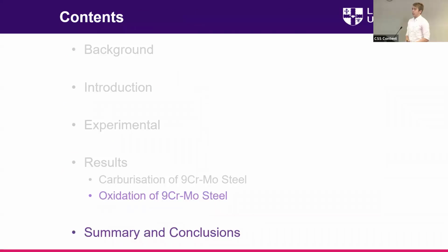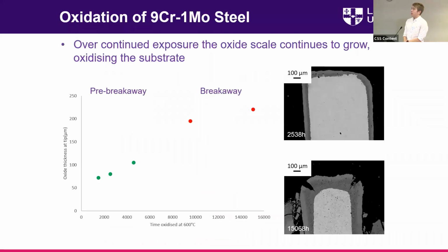So yeah, now I'm going to move on to talk about the oxidation of 9Cr-1Mo steel. With the continued exposure, the oxide scale continues to grow. The one on the top there is exposed for about 2,500 hours, and the one on the bottom was 15,000. So it increased from about 60 microns thick to about 230 microns thick at the fin tip.